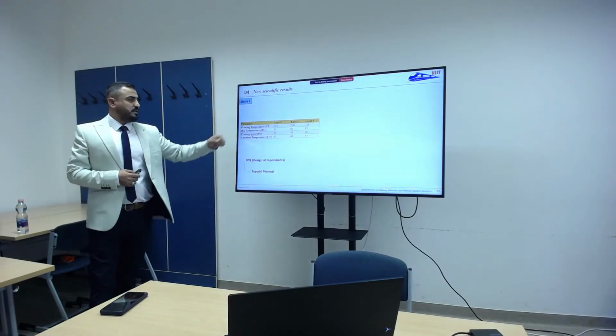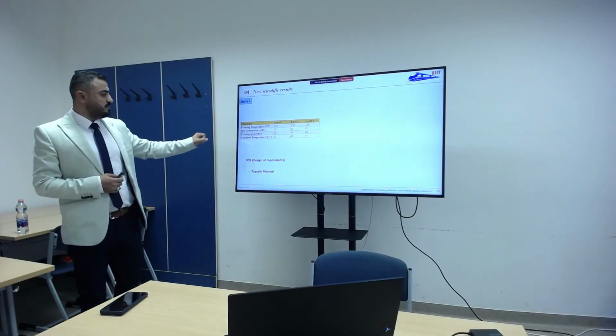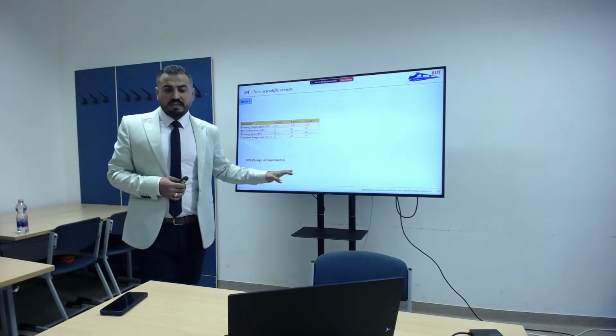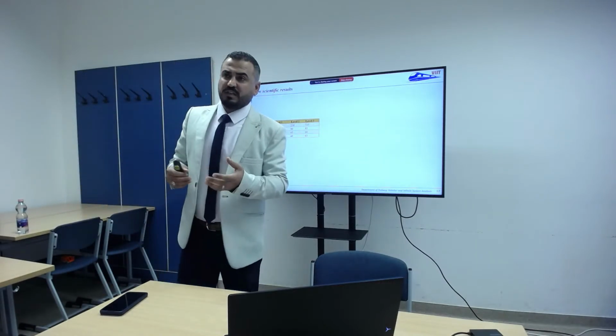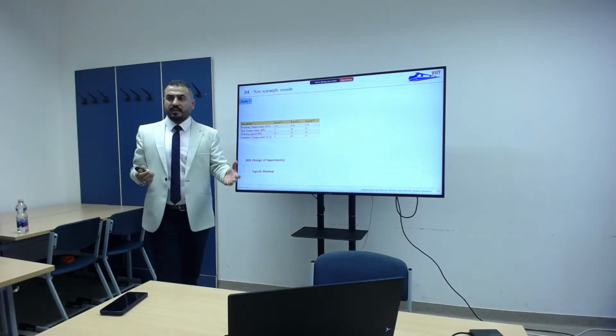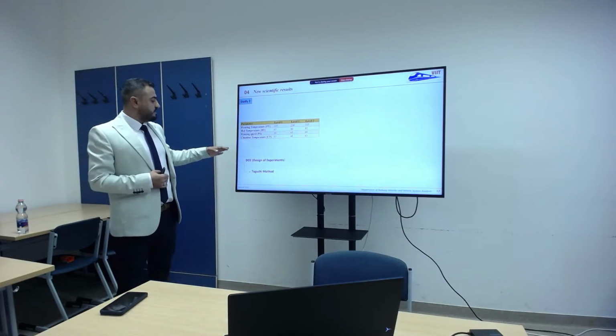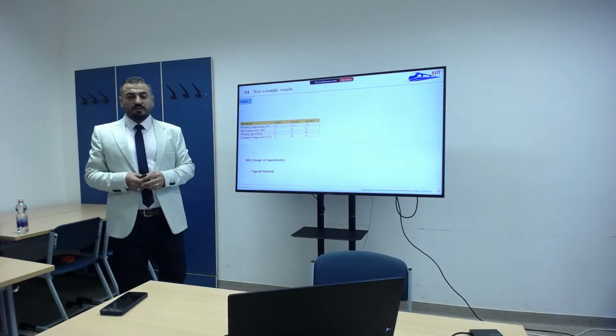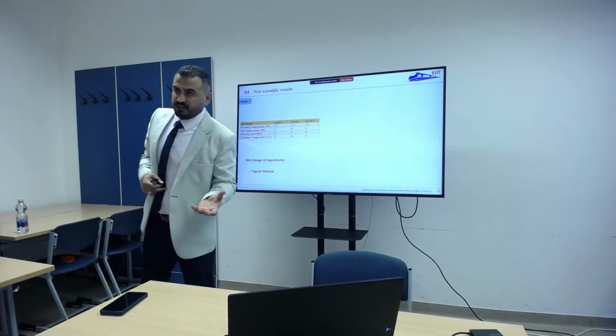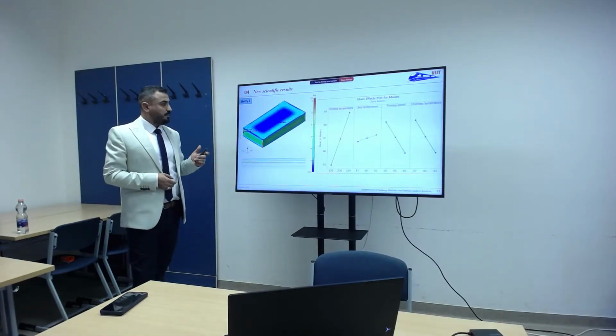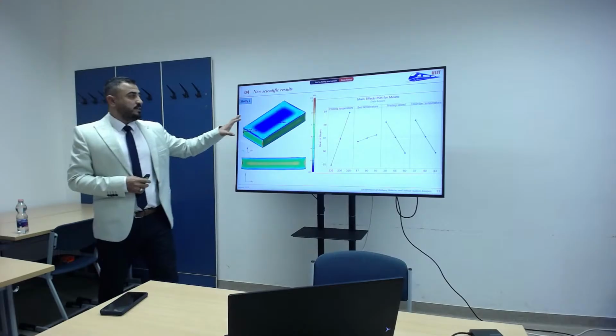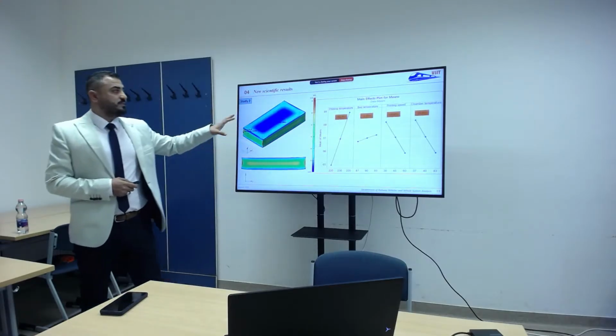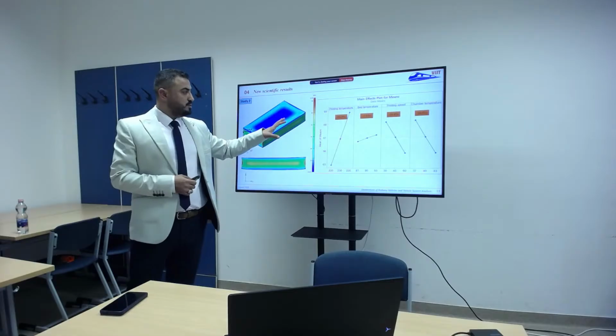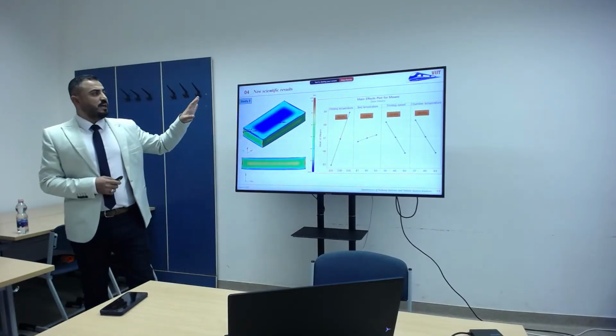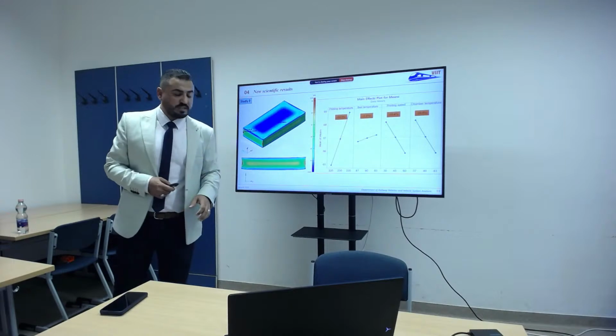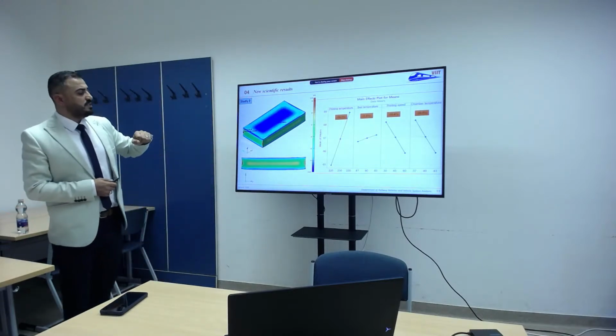In this study, I studied 3 different levels for each parameter. I used design of experiment, which, as you know, is a structured approach to determine the relationship between input and output. From the design of experiment, I used the Taguchi method because it depends on minimizing the variation to improve the quality. And the results showed that the printing temperature was the most dominant factor, with about 60% contribution to minimizing the residual stress, followed by printing speed and chamber temperature at about 20%, and the bed temperature at around 1%.